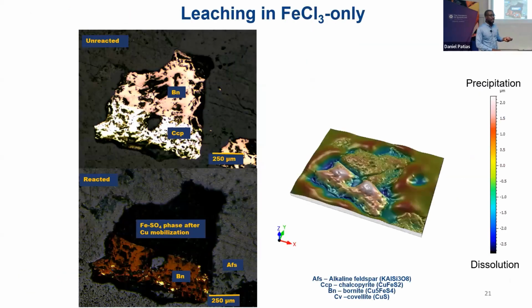If we put in ferric, so at low pH conditions, what we observe is that if you have bornite lying side by side chalcopyrite in your fresh surface, after 30 days of dissolution, you have copper mobilized from your bornite. It leaves behind something like a ferric sulfate phase. And then your chalcopyrite is bright yellow, sort of transforms to more bornite rather than dissolving.